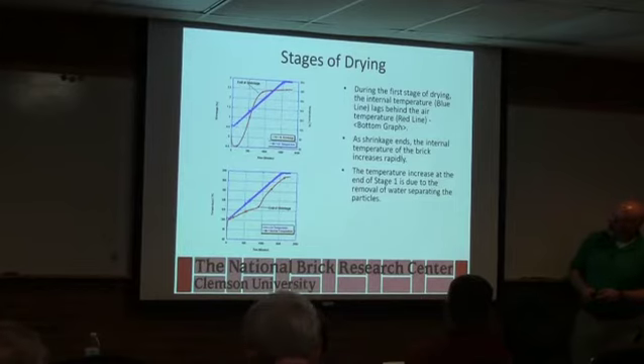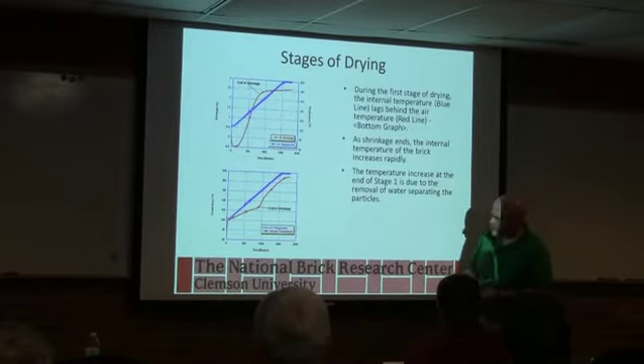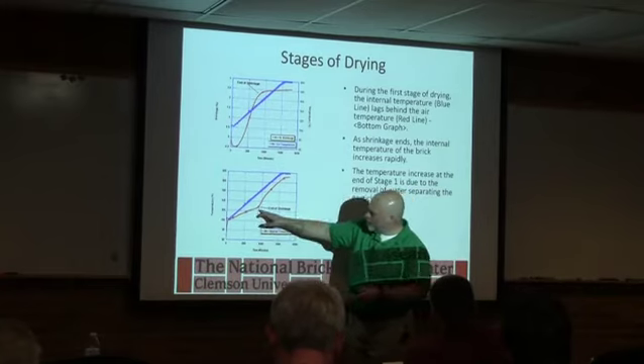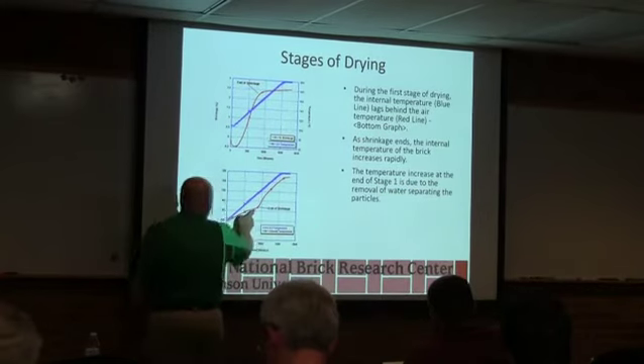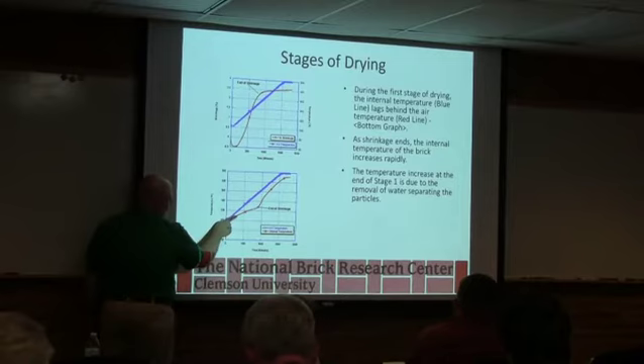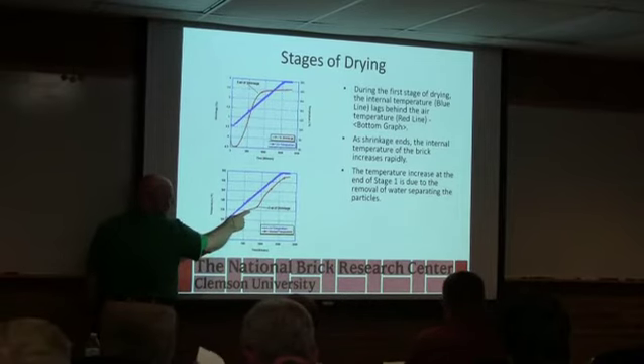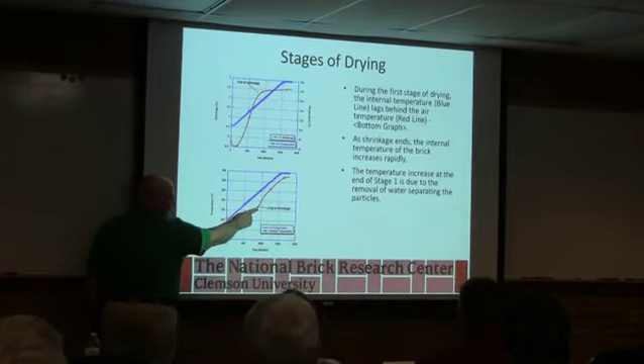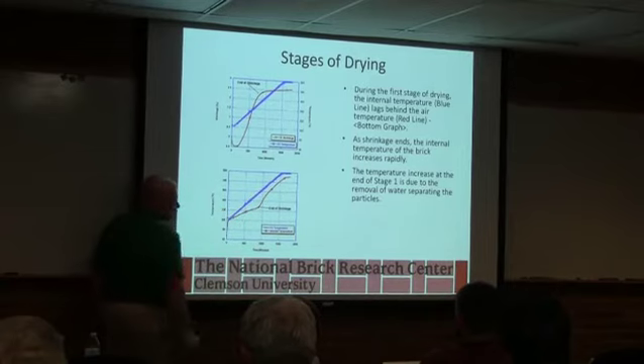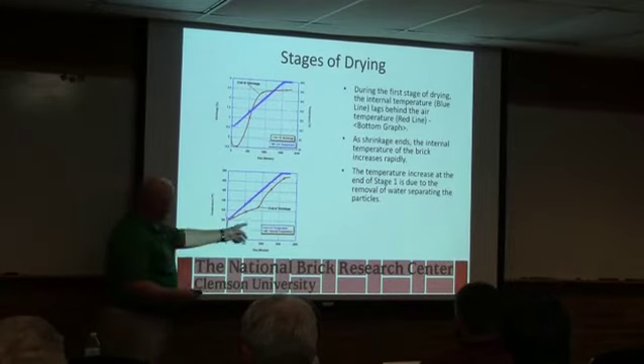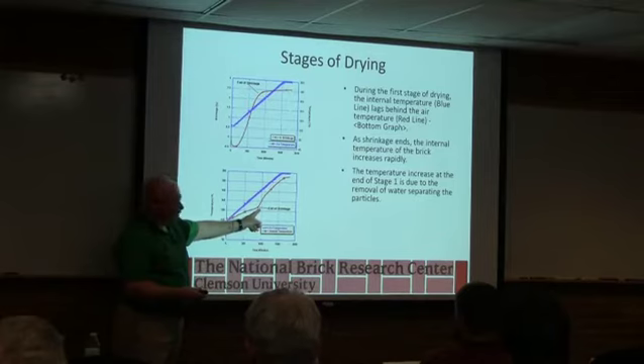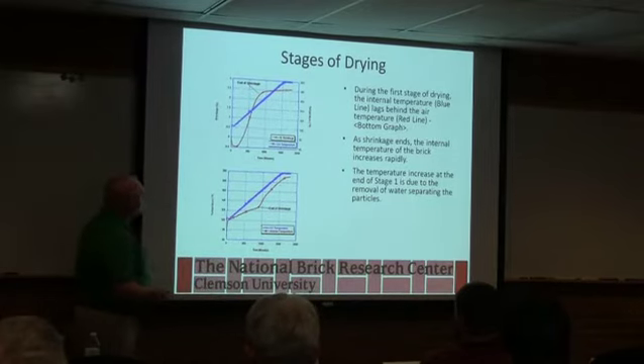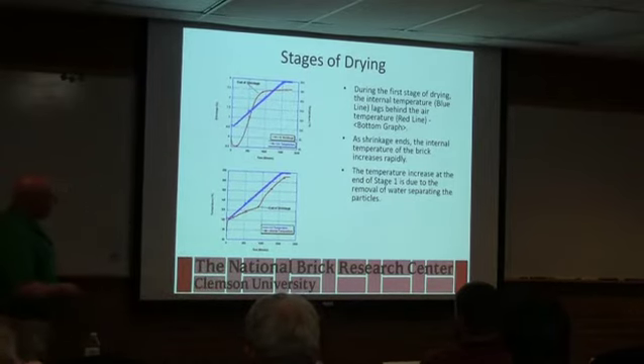So we can go through and do different tests, but this is the one I was interested in. If you put a thermocouple on the surface of the brick and you monitor the air temperature while shrinkage is taking place, and that's also where evaporation is at the surface, you see your temperature kind of lagging behind until you get to the point where shrinkage stops, and then it starts to catch up with the air temperature. So that's an old trick to find out in the dryer where shrinkage stops. I rediscovered it accidentally until Don Dennison told me I was an idiot.